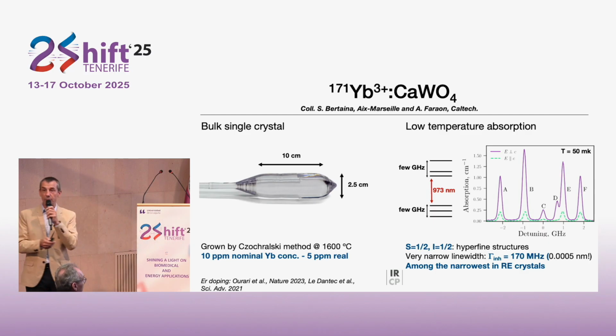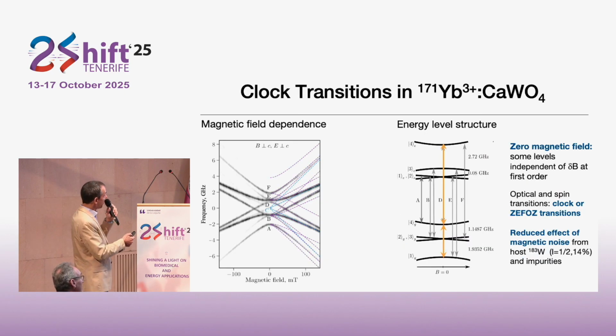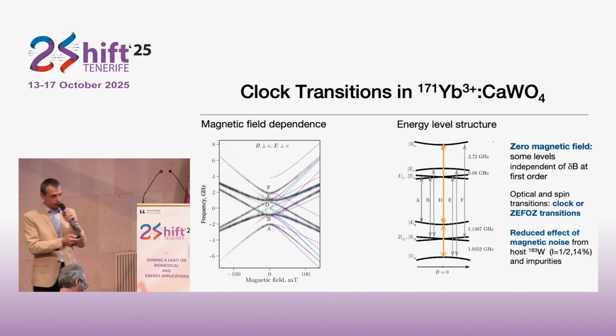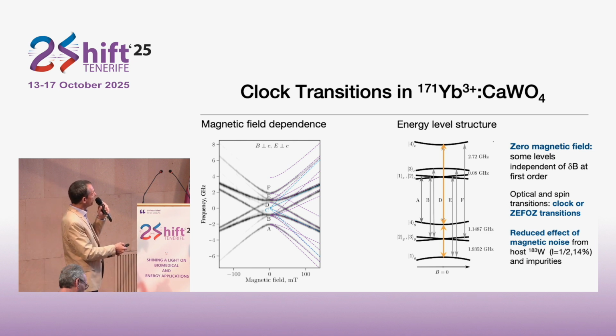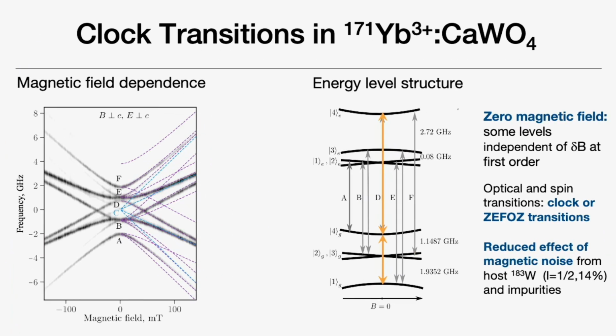Now, to understand a little bit better what the structure is, we turn to an experiment where we apply small magnetic fields on the crystal. And here what you see is that from the situation at 0 magnetic field, which I just showed you, when you apply a magnetic field, you start to see fairly complicated magnetic field variations for the transitions. Each vertical slice on this graph is a spectrum as a function of magnetic field. You see that different lines are appearing when you apply a magnetic field. Some degeneracies are lifted. But as you can see also on the right side, based on spin Hamiltonians, we can fairly well simulate these lines.